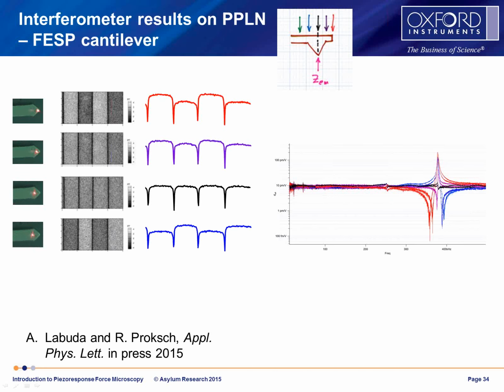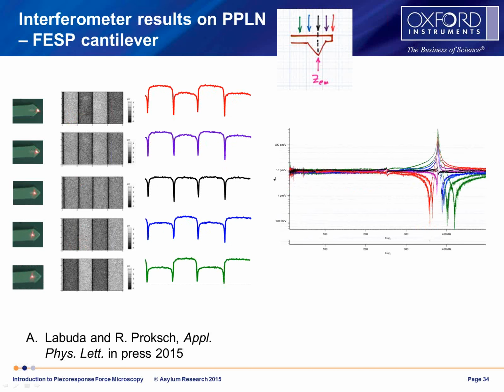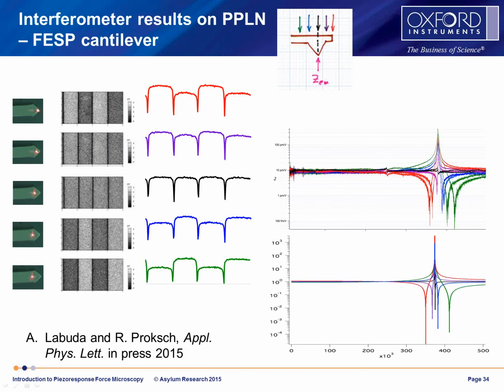If we continue to walk that spot a little bit closer to the base now, you see that this domain structure going from bright-dark actually goes to dark-bright, so that switches around as we would expect. And as we go a little bit further, you can see that even gets more enhanced. And these tunes here show that as we add that in there, you can see this antinode goes from below resonance to above resonance. Now you can also simulate this using that Euler-Bernoulli mathematics that we've already discussed. I mentioned that the average value is about 9 picometers per volt, but the simulations come out like this, and the reproduction is quite good.